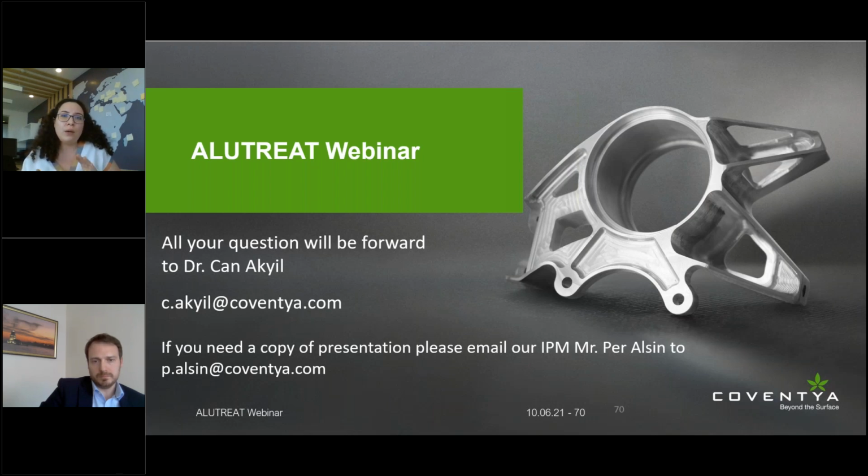And the second one, I believe, is smut formation. Actually, smut formation is quite the opposite of stickiness. If we overseal the surface, we end up with a dusty finish. It can be aluminum hydroxide, or if we discuss cold seal, it can be aluminum fluoride and nickel fluoride.